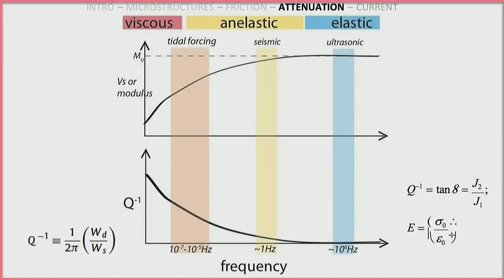And this is a cartoon of the general shape of these curves. So we have the modulus at the highest frequencies, like if you shot ultrasonic waves through something, the values you would get for modulus are pretty close to the theoretical unrelaxed modulus. But with frequency, this weakens. In the same way, the inverse response is the attenuation, which we denote with this Q. And again, I don't actually model the heat, but this is what is used. Attenuation is what's used to figure out the energy dissipated versus the energy stored in a system.